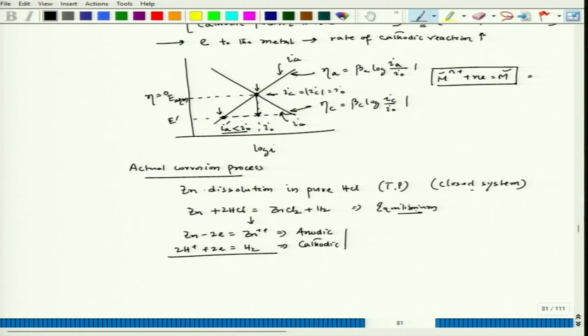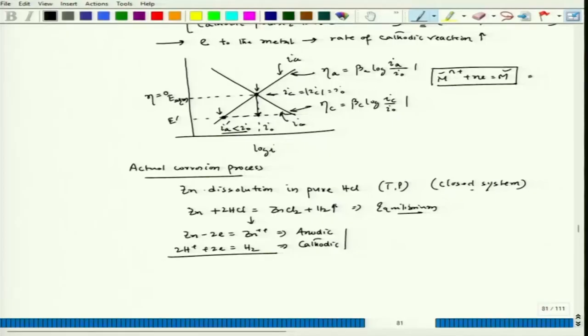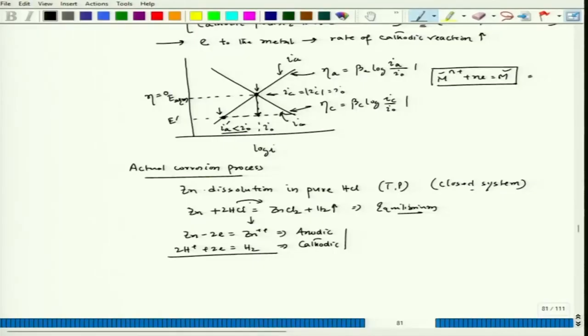But actual corrosion system does not maintain equilibrium. This is an open system and hydrogen is a gas. And that hydrogen gas has the ability to go out of the system. And if hydrogen gas goes out of the system, in order to maintain equilibrium, because if you fix temperature, then definitely this particular system would like to go to the equilibrium. So, in order to maintain that equilibrium, Le Chatelier's principle would come up, so the reaction would always go this way. Okay.